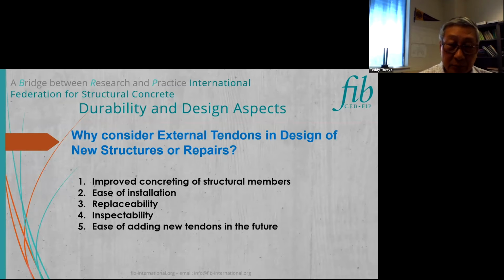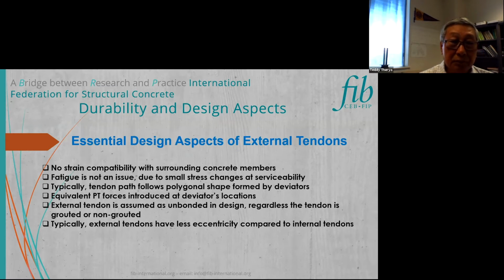If you have any issue of deflection, for example, in the structure, you can add future tendon. So make sure in our design, we prepare an extra hole in the deviator and also in the diaphragm for this future tendon. This is an essential design aspect of external tendon. We also need to be aware that the behavior of external tendon is quite different from bonded internal tendon, especially beyond the cracking level of the structure. We all know that there's no strain compatibility in external tendon with the surrounding concrete, and this is quite different behavior from bonded internal tendon.